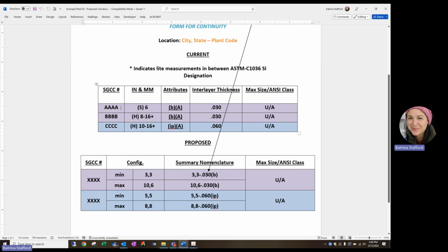The colors were used to help correlate between the 2 charts. So starting with this product here, AAAA, it is a standard product that has a nominal thickness of 6 millimeters, using an 030 PVB inner layer and a base glass kind of annealed glass. We have another product, BBBB, that is within the heavy category, a nominal thickness range of 8 millimeters to 16 plus, using an 030 inner layer, PVB, and a base glass kind of annealed glass. We were able to condense these 2 products down to 1.